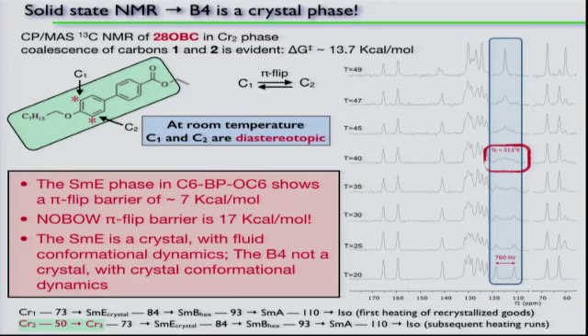They're just really slow. Okay, so what's happening is the barrier is 13.7 kcals per mole in this case, which is a pretty high barrier, and the exchange is slow. And I'm not sure exactly what the rate is, but it's pretty slow. But you can easily measure that. This is a kind of real-time quantum mechanics going on here. And when you see this coalescence, it tells you how fast this exchange is happening, the site exchange, how fast these two things are exchanging locations. And in the crystal, they sort of flip.